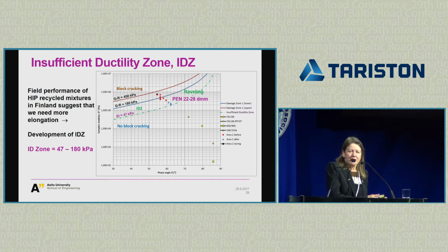So combining this idea with mixture behavior, we developed a new zone, which we call the insufficient ductility zone. So it's there between 47 and 180 kilopascal area. So what does it mean? Well, very simply thinking, nothing is simple, but let's say that if we try to simplify it a little bit, if we are between 22 and 28 penetration, we might get in trouble with raveling and poor performance. So it gives us some indication of where we should be when we have finished the recycling work and check what we have in our hands.